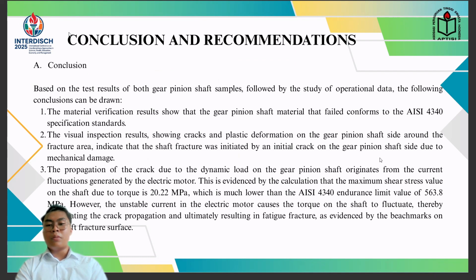This is evidenced by calculation showing that the maximum shear stress value on the shaft due to torque is 20.22 MPa, which is much lower than the AISI 4340 endurance limit value of 563.8 MPa. However, the unstable current in the electric motor causes the torque on the shaft to fluctuate, thereby accelerating the crack propagation and ultimately resulting in the fracture, as evidenced by the beach mark on the shaft fracture surface.